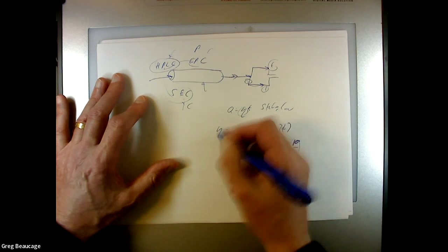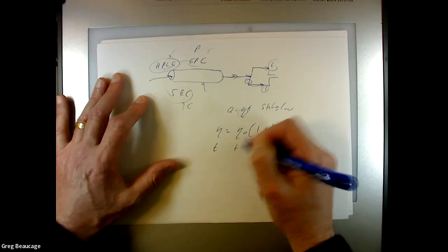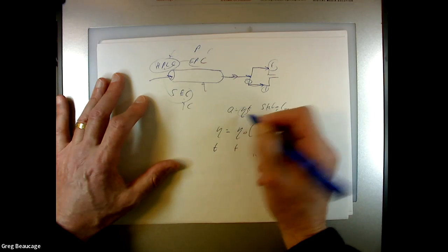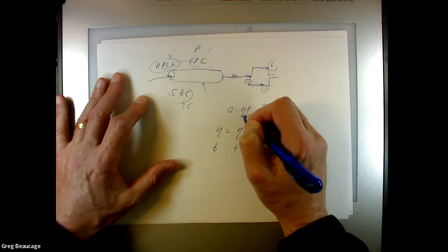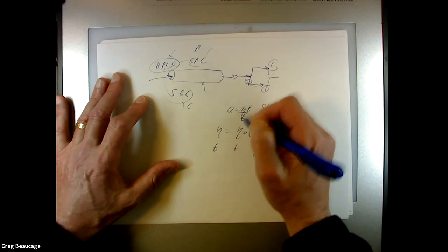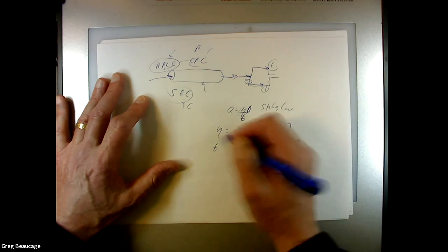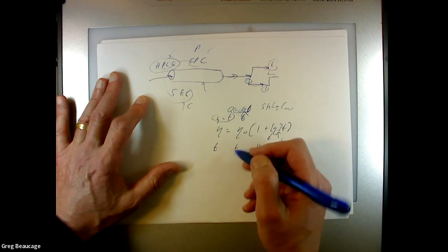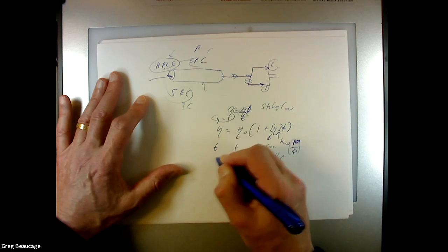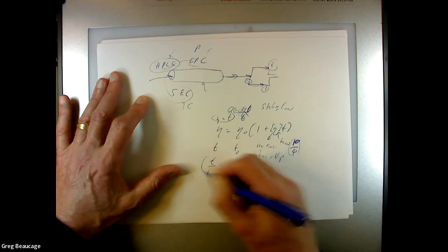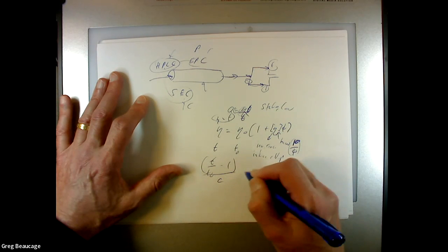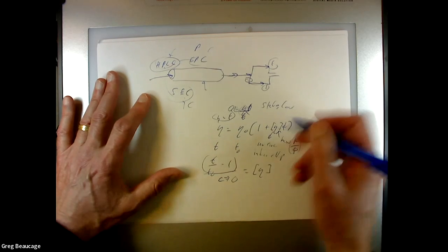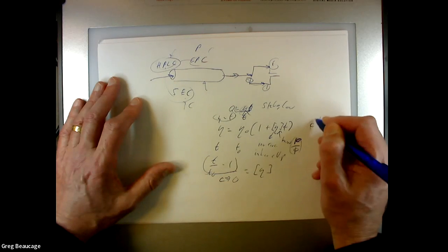Anyway, you can swap out. If you have the time for these things, you have this upside down. The flow rate, the longer the time, the higher the viscosity. So it's inverse to this. Anyway, viscosity is proportional to time. So you have time and time, and you can take the ratio of the times, T over T0 minus 1. Then if you divide that by the concentration, you get this intrinsic viscosity, as long as your concentration goes to 0, because you don't have effects of binary interactions like these other terms.